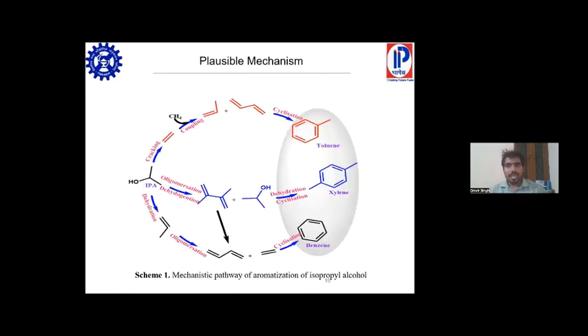Then come to the mechanism pathway. As we found, IPA first goes to cracking to give olefin type, which was oligomerized to give diolefin, and diolefin and monoolefin cyclized to give monoaromatic, and some of the monoaromatic is linked with the olefin to give ethylated product, that is toluene or ethyl benzene or xylene.